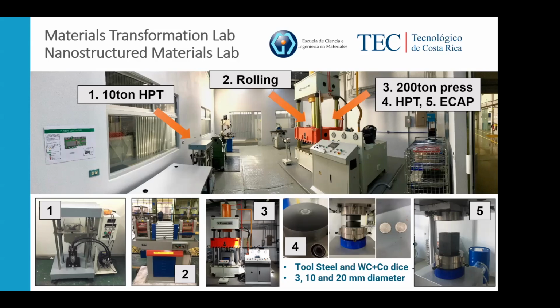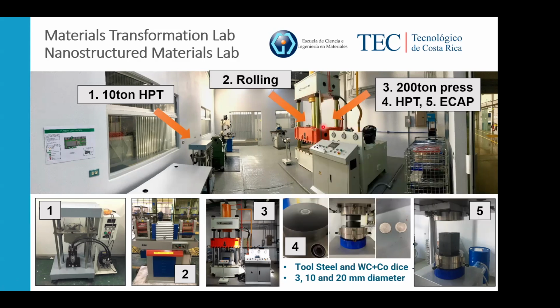And then we were able to upscale our HPT facility to the machine you see, number 3 over here. I think I can use a pointer probably. So the machine over here, this is the time that we installed the hydraulic press. It's a 200-ton hydraulic press. And in this 200-ton hydraulic press, we designed and installed a torsion system. And the torsion system was developed here locally. And it has a little bit over 6,500 Newton meters of torque. So it's a very robust torsion system.